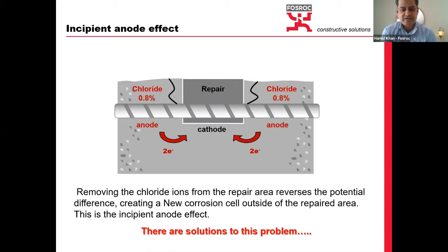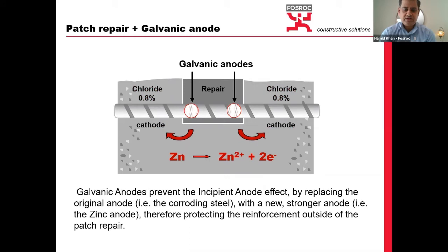We have done a great job, excellent surface preparation, very good saw cutting. We've gone beyond the steel rebar and all that, but it could still affect the adjacent areas. So the solution, which most of the specifications call for, is to add galvanic anodes at the perimeters to extend the boundaries of protection. These anodes have a radius of effectiveness and can protect the adjacent areas as well. I have tried to show it in a small animation. Let's see if the technology works. Graham, I'll just play it, and just give me a thumbs up if you can see that.